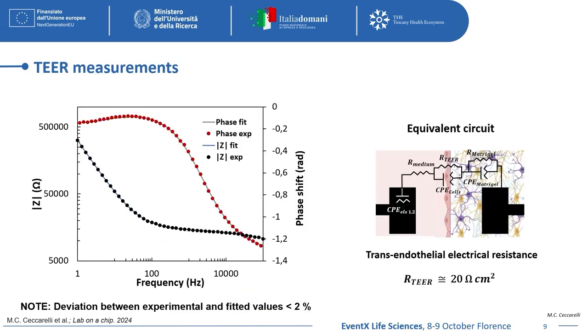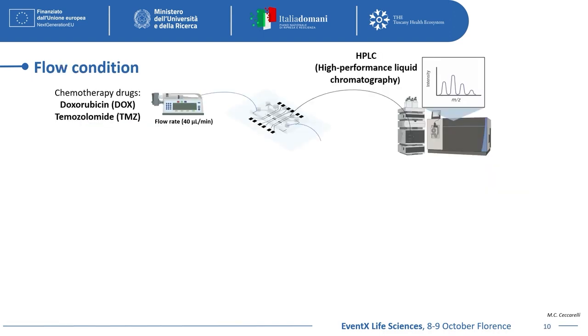Then we also model an equivalent circuit in order to take into account each compound, the Matrigel, the cells, and the media, to extract one of the most relevant parameters for the BBB, the transendothelial electrical resistance, the TEER, and we were able to obtain a deviation between the experimental data and the fitted value, thanks to the equivalent circuit, of less than 2%.